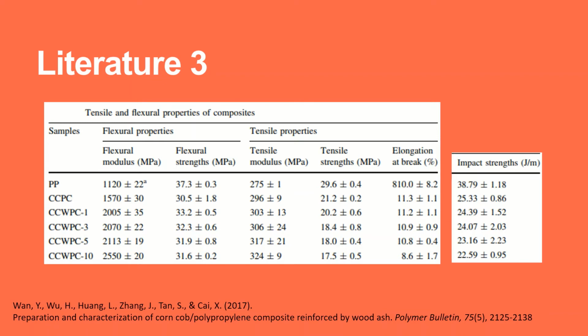of the sample. The composite with 10% weight wood ash possessed the minimum value of elongation at break, which is 8.6%. This consequence was in accordance with a rising stress concentration point, which might lead to the brittle behavior of the corn cob flour wood ash polypropylene composite.